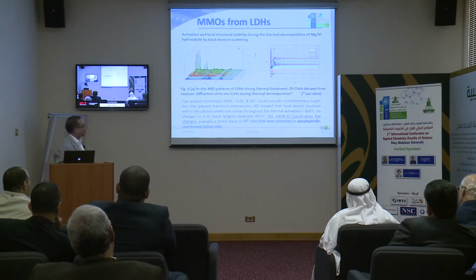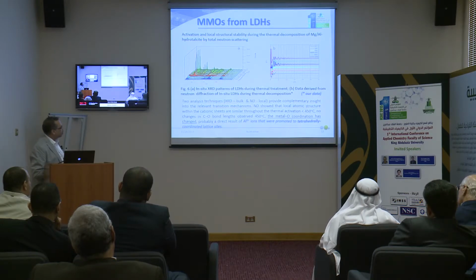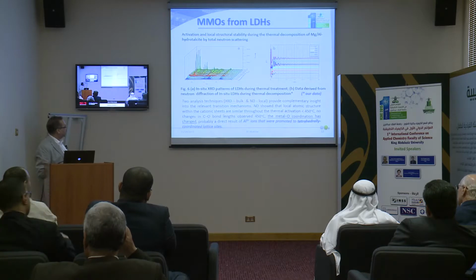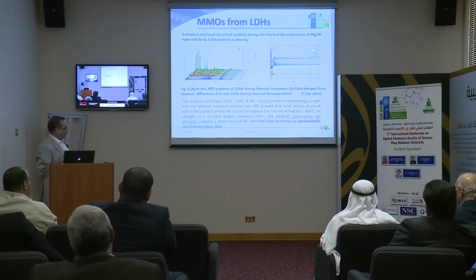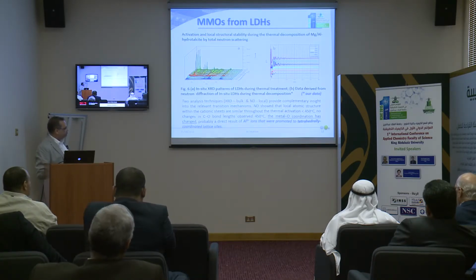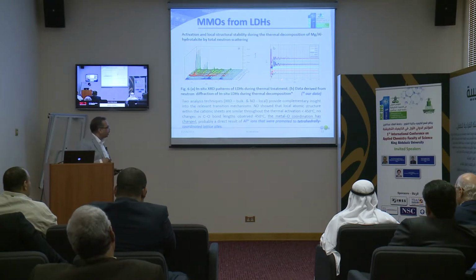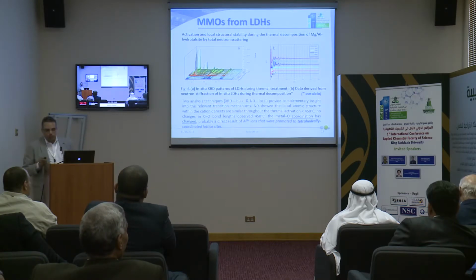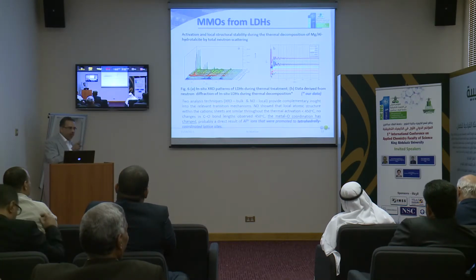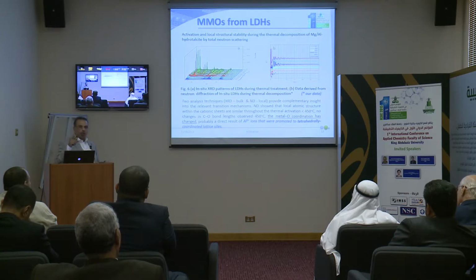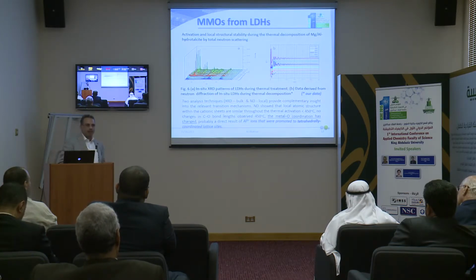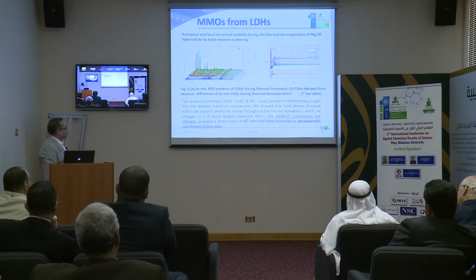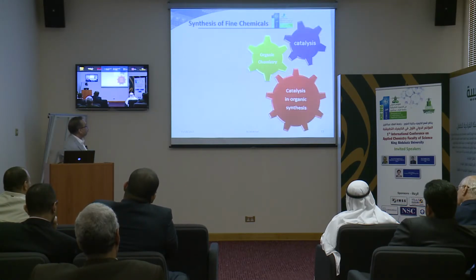And at the conclusion from such nice work already published in Chemistry of Materials, Materials Chemistry, and Clay Science, we could say aluminum trivalent ions were promoted to tetrahedrally coordinated lattice sites. This is very important because you now move the cation from the octahedral site to the tetrahedral site, and this will affect the catalytic activity, or explain to us why this catalyst is very active in certain processes.